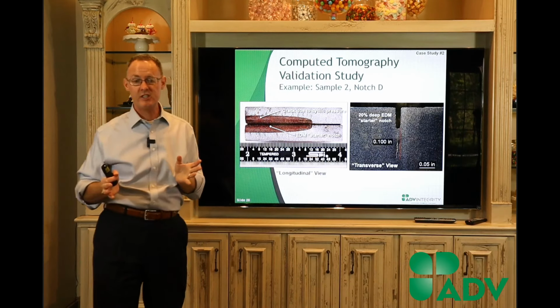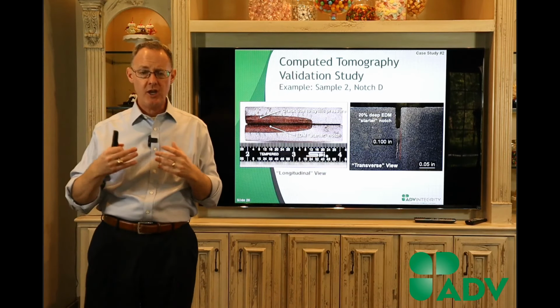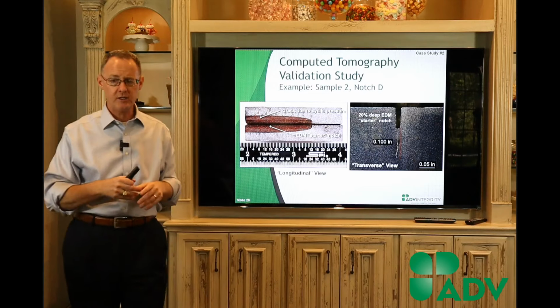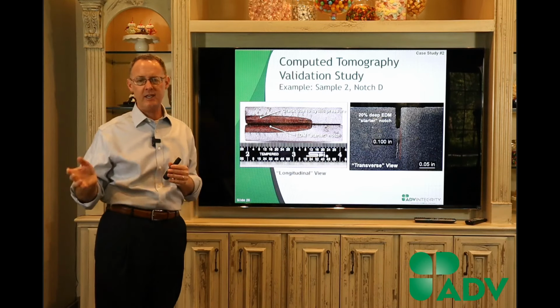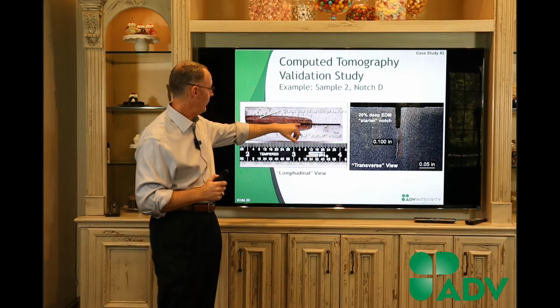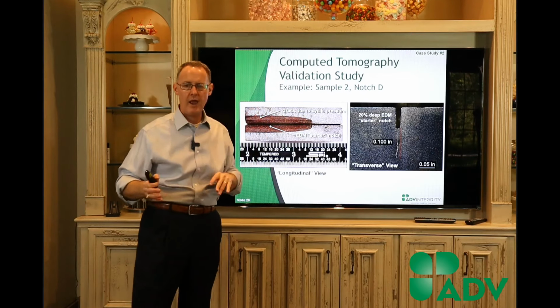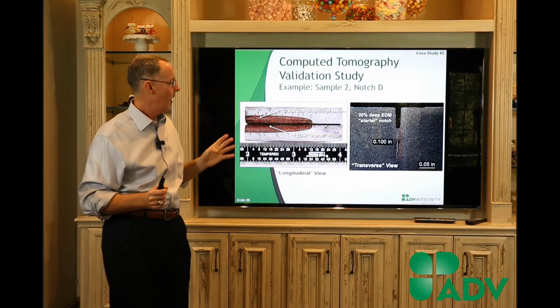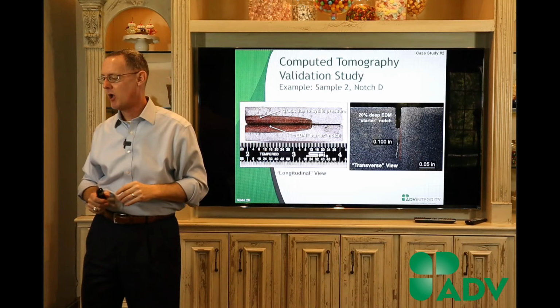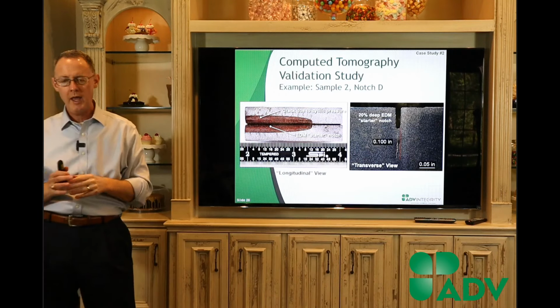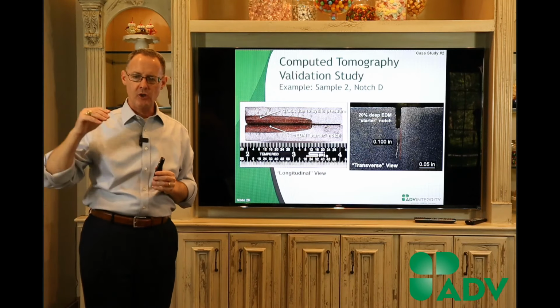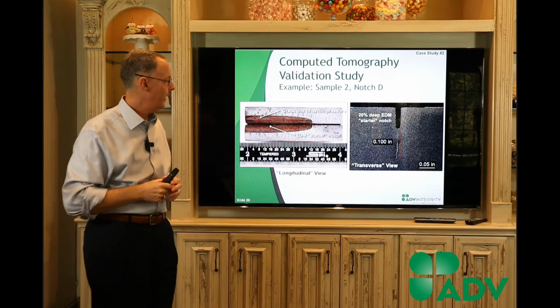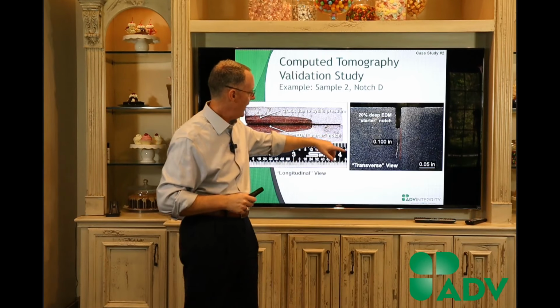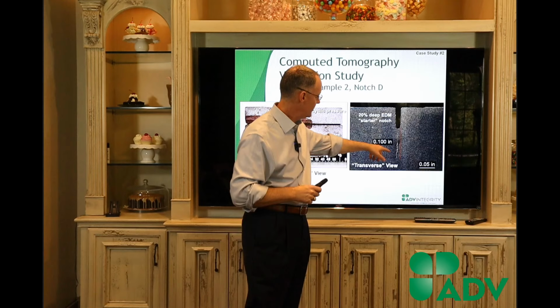We obviously stopped it, okay, so that James would be able to make the inspection work. And so we break it apart. If we had continued cycling, that rusty area would have gone all the way through, and we would have had a through-wall defect that would have developed. On the right side, you can see what I'm calling the transverse view, and that section right there is looking down the axis of the pipe. And so you can see the EDM notch, and you can see how much our crack grew in that process.